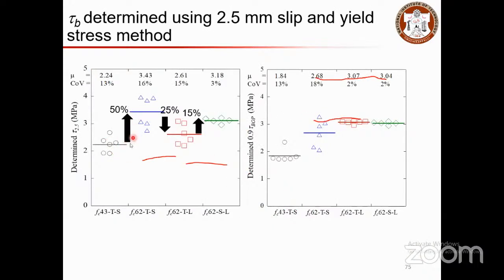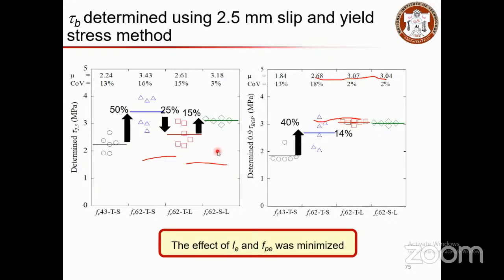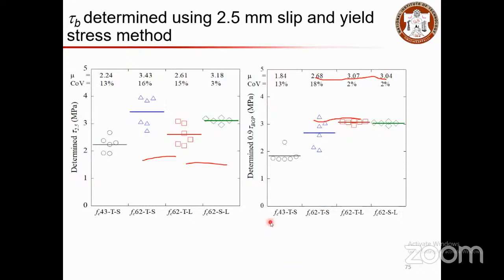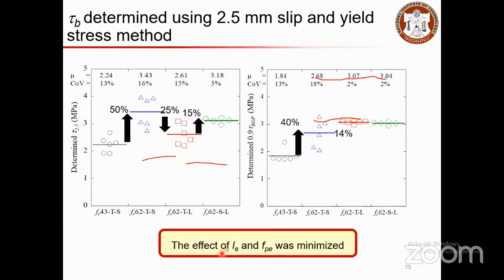So we understood that when the tensile stress increases, bond stress increases, and when the length increases also, bond stress increases. This is for the short span, this is for the long span. So from this, when we use the effect of embedment length, the defining method is very big. Instead of 2.5 mm slip, you consider the point where the behavior changes. By considering that, we could eliminate the total embedment length effect, and we can eliminate the effect of pre-stress; those things could be minimized.